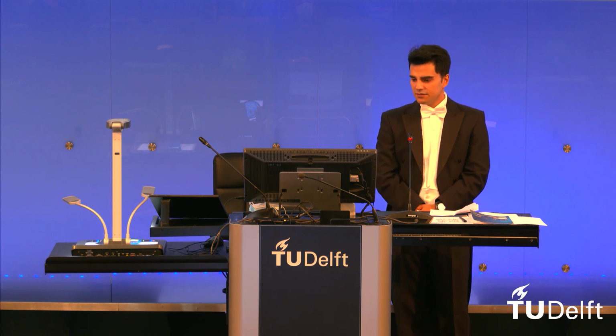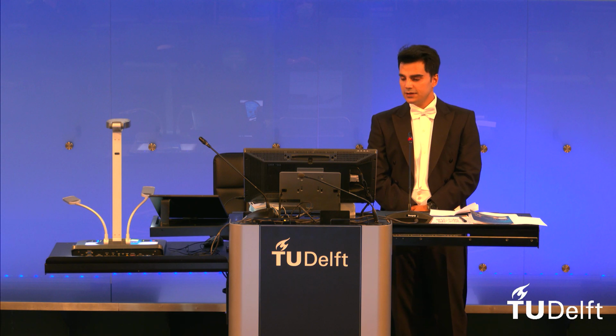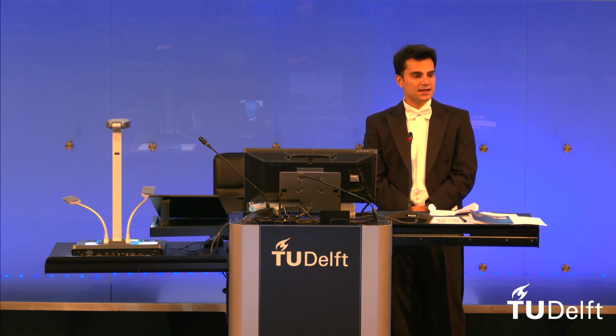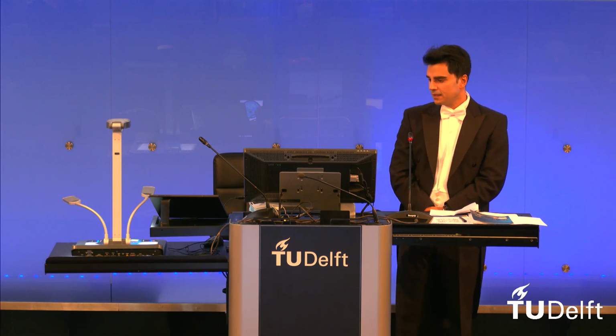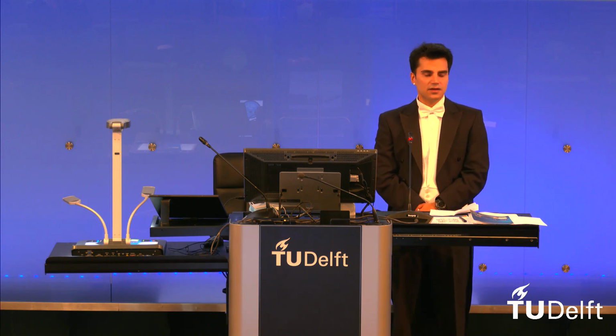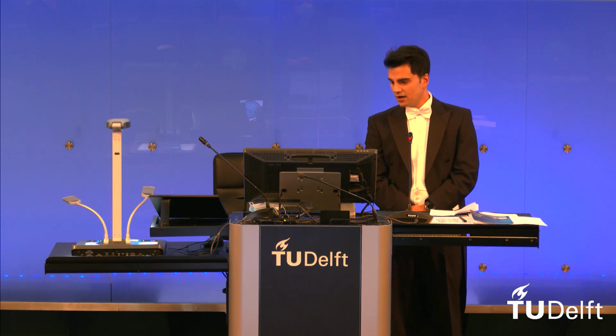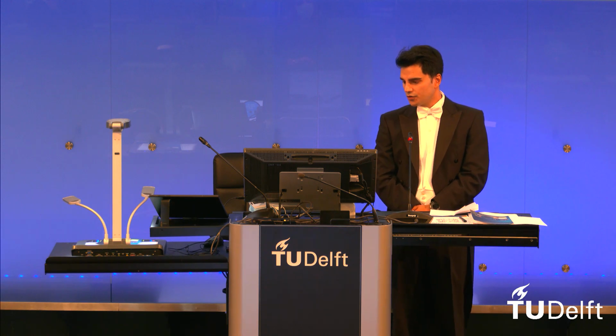As you see, the left one is the result of thermomechanical modeling. The middle one is the result of CT scanning. You see the red area, which is the crack under the rail surface, which has been made transparent compared to the bulk steel in order to be able to see that. And the last one is the result of a preliminary test with the new test rig to see how it operates and how it works.